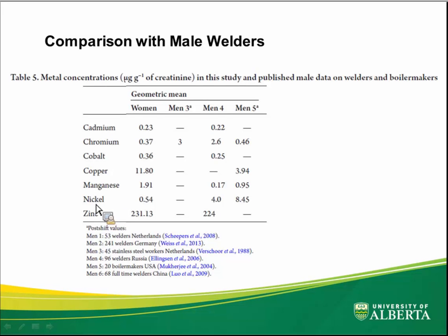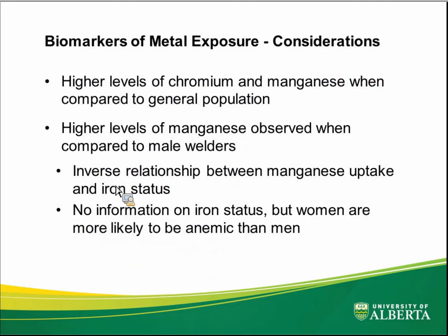Quite a diverse set of groups for comparison, to be honest. And if we go down and make the comparison across, the copper value for the geometric mean is almost 4 times higher, or 3 times higher, pardon me, than the American Boilermakers. And the manganese, again, is seemingly quite high, twice at the highest, so 2 times higher than the American sample. The nickel level is the one that does appear to be lower than the male welders, and this holds when you look at the other measures, so the median and the range as well. So it looked, for the comparisons with men, that the copper and the manganese are higher and that the nickel might be lower. But again, we're comparing two very diverse populations.